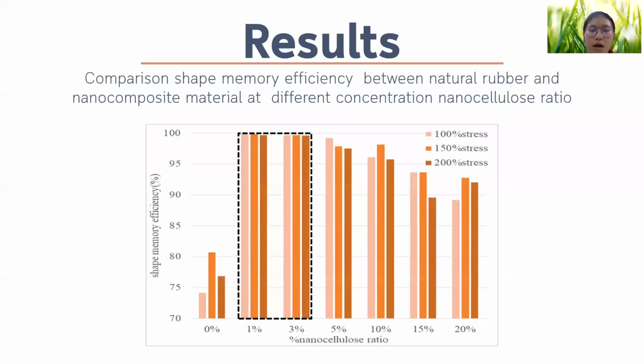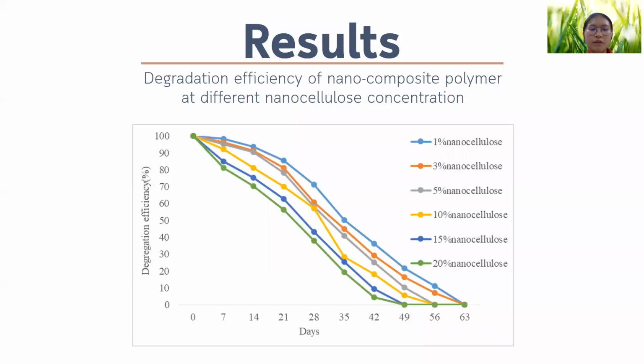These results show the efficiency of the shape memory property in the composite polymer. You can see that 1% and 3% nanocellulose have the highest shape memory property because of the natural rubber content in the nanocomposite polymer. It has an alkene group in natural rubber that increases shape memory property. This graph indicates the degradation efficiency of the composite polymer. The degradation test found that 20% nanocellulose is the best concentration for degrading, at 49 days, and 1% nanocellulose is the lowest concentration for degrading, at 2 months, because 1% nanocellulose has a strong cross-link bond.